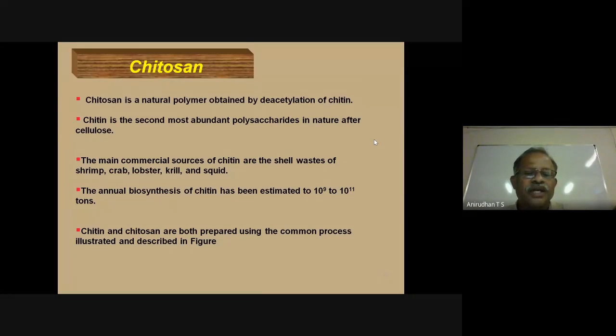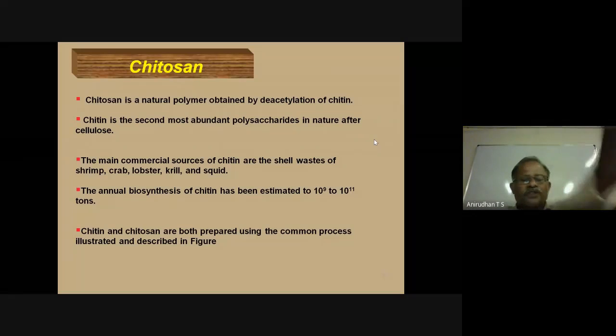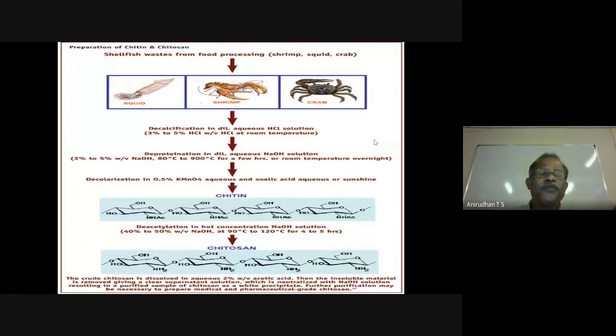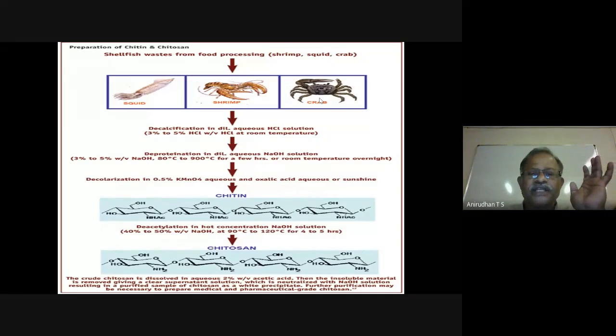You can easily collect chitosan from the exoskeleton of species like shrimp, crab, krill and squid. Chitin and chitosan are both prepared using a common process: you remove the flesh, and we have an exoskeleton of squid, shrimp and crab, made up especially of calcium carbonate. The first process is decalcification with dilute aqueous HCl. You treat the shell with the dilute aqueous solution and decalcification takes place, followed by aqueous sodium hydroxide treatment, where deproteination takes place and proteins and other chemical species disappear from the skeleton. Finally we treat with 0.5% potassium permanganate aqueous solution and oxalic acid to obtain a crystalline material.